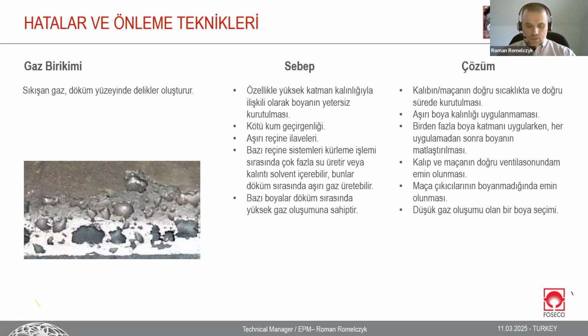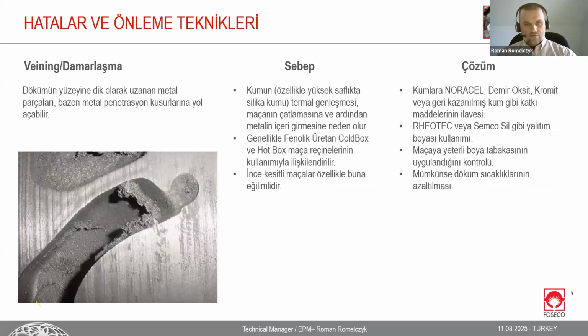Yes, the final one, not final, but it happens very often, mainly in automotive, or maybe not automotive but mass iron production: veining. Veining comes from sand expansion, the sand mold and core expansion. An additional rate of binders gives a heavier effect because it's more stiff. So expansion will quite easily create gaps, breakage.